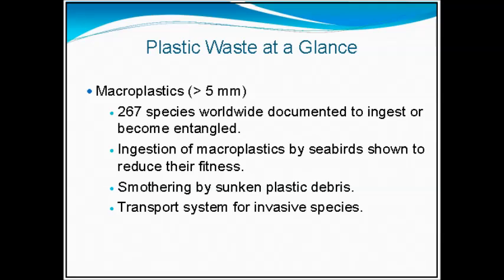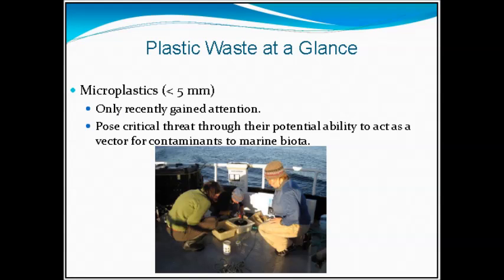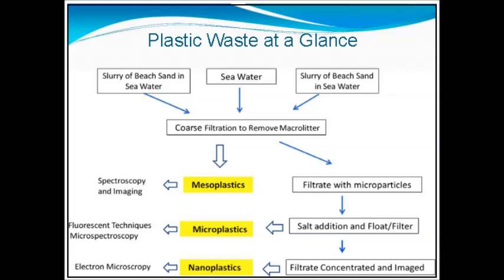And so only recently have people gone out there and collected some of this material by running some kind of a net through the water, and then isolating the actual particles and figuring out what they are in terms of size and description. So this is an example of a classical separation scheme where people have collected water, beach sand material, and so on, and then done filtration, isolation, and you can see the level of analytical technology that's applied here, all types of spectroscopy, even down to electron microscopy for really small particle size. So we're going from large particles down to the nanoparticle level to determine what's really present in these materials that are present in various sample types.